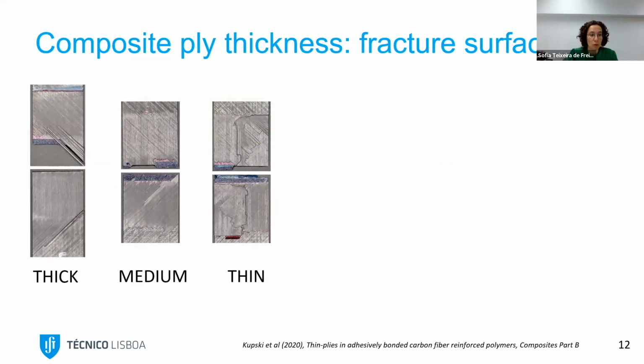So these are the first results, and what I'm showing you here is the fracture surfaces. Once we broke the specimen, we looked at the surfaces where the fracture occurred. They normally give you a lot of information about what happened. So here for the thick, for the medium, and for the thin. What we first see, which is pretty clear, is that almost everything is black, which means that the crack propagated mostly in the composite. The adhesive that we had was a pink adhesive, AF163-2, which is commonly used in aircraft structures. You see a little bit of adhesive there, a little bit there and there, but most of it is only composite failure.